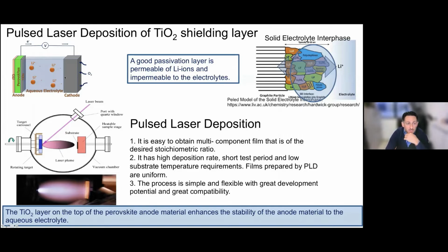So at that time, we realized that pulse laser deposition is a good candidate to obtain this kind of layer. Through the literature search and many theoretical studies, we came to the conclusion that a shielding layer of titanium dioxide should be quite effective and reasonable to have. So why pulse laser deposition?